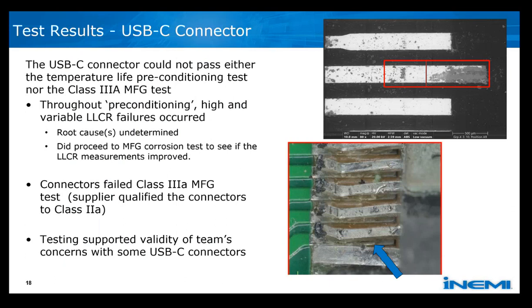Next slide, please, Mike. Unfortunately, we found, much to our surprise, that we were starting to see some failures, some high contact resistance measurements after some of the temperature life preconditioning testing, and then into the mixed flowing gas corrosion testing. Honestly, we were so surprised at the temperature life failures. We did pull out one connector of each test group to examine, to perform failure analysis to see if we could determine what was going wrong.